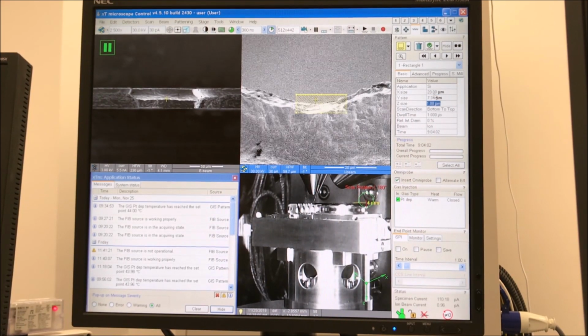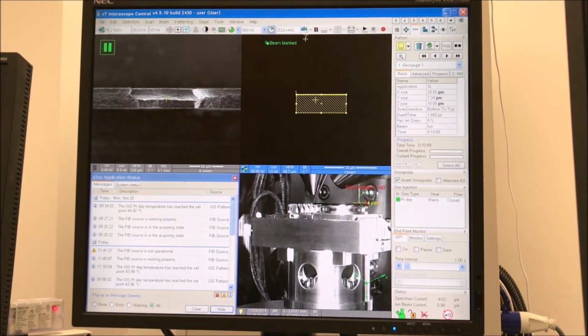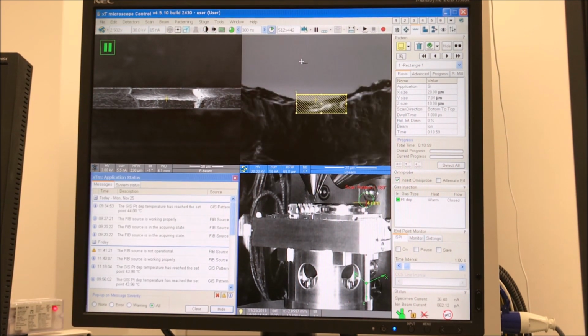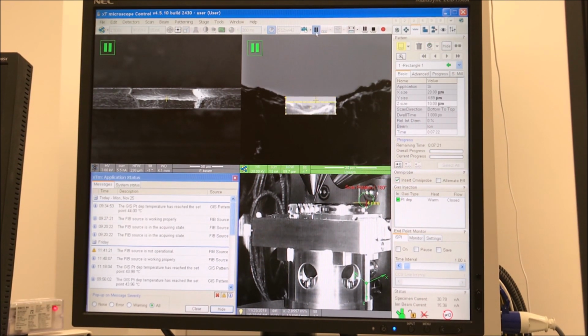So to facilitate easier lamella attachment, one thing I like to do is to cut a shelf into the middle of the post. And so for this, I'm using a fairly high current. This is 15 nanoamps and just a rectangle pattern. This is about 20 microns wide. And I'm using the live ion beam image to see my progress, or I should say the live ion beam signal from the area that's being milled to see the progress. And so this is going to make it easier to attach the lamella because I have this nice flat shelf in the post.